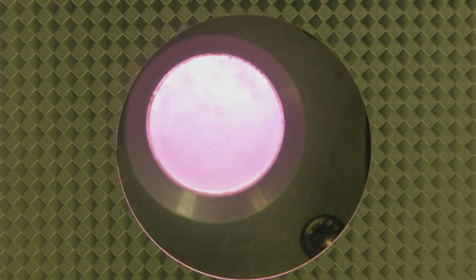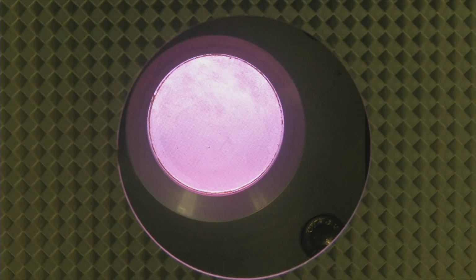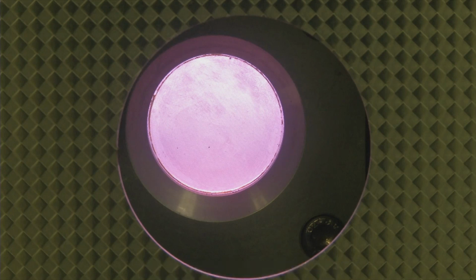So once we achieve the right pressure and gas combination, what you see here is the flash of the plasma. Here, what is happening is the first step of the etch process, where we are trying to etch silicon nitride anisotropically. You can see this nice color coming out of the plasma because of emission that we saw in the dry etch. The emission comes from the various gas molecules that are excited, and when they come to the ground state, they emit photons, right?